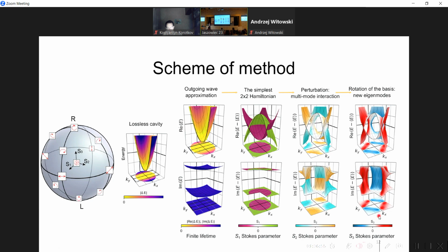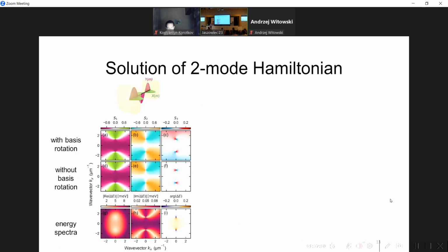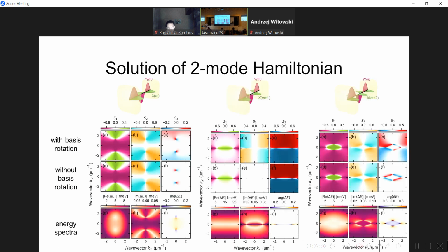Now I present the spectra for the upper branch for three different regimes. This is very similar to the picture presented at the bottom of this figure. So we have three different regimes in our cavity, and here you see the polarization pattern when you include the rotation of bases, here you see the polarization pattern when you don't take into account the rotation of bases, and here you see the difference between the energy of the two eigenenergies of our Hamiltonian.